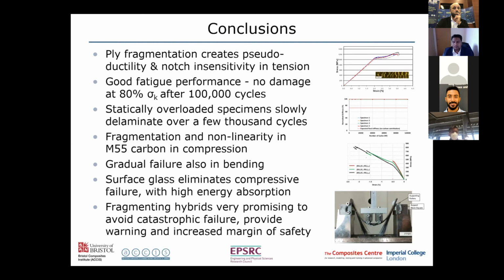So if you just take that on its own, you could take 1.8% up to 2.3%. That's a huge increase in tensile failure strain just for the same fiber, in addition to getting the benefits of the fragmentation, the pseudo-ductility. So I think it's a very interesting area to take advantage of a greater proportion of the real true strength of the material.